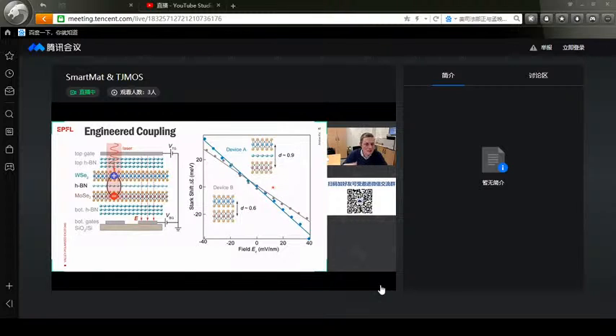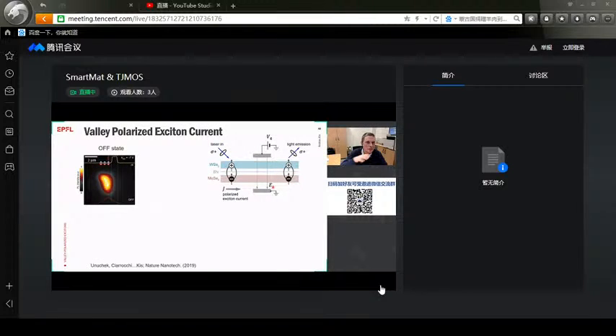And now the excitons, since the Moire potential is weaker, are free to move, so they can now diffuse, just like in the beginning. But since the optical transitions are direct or more direct in K-space, they also preserve polarization. So now when we shine a circularly polarized laser, we create excitons which are composed of spin up electrons and holes, and they diffuse. But this diffusion is now also a diffusion of spin polarized excitons.